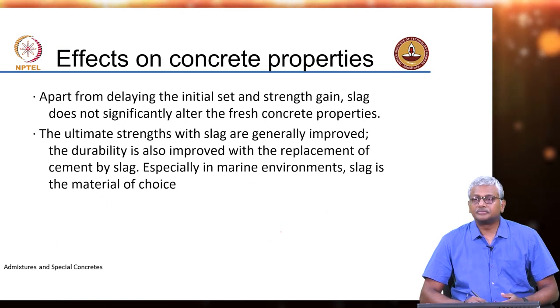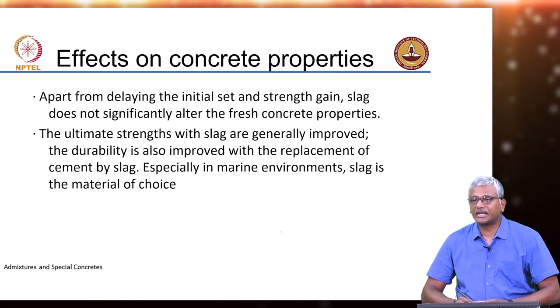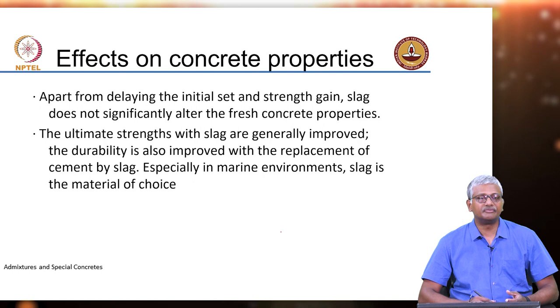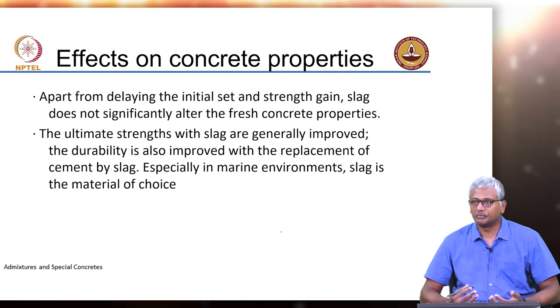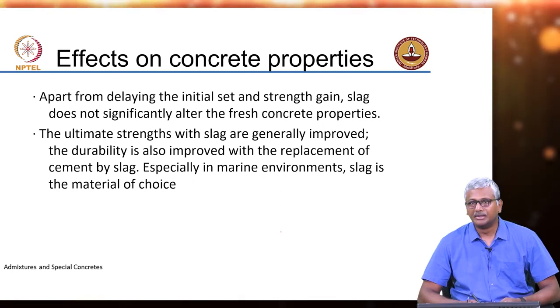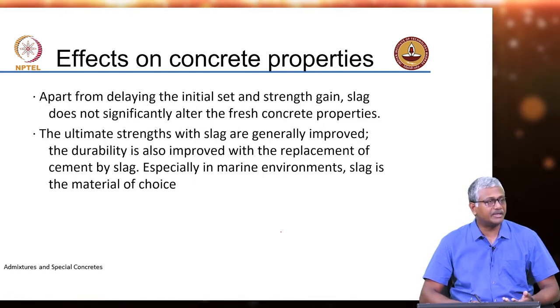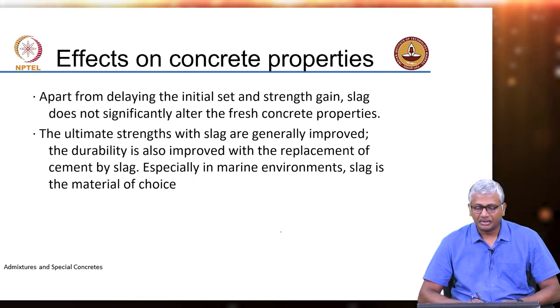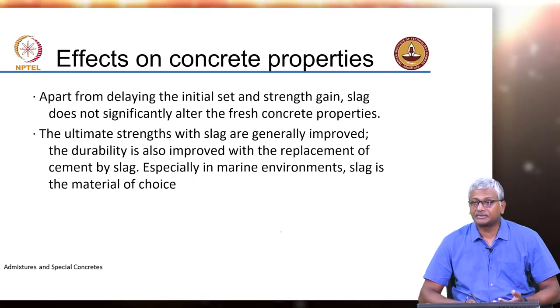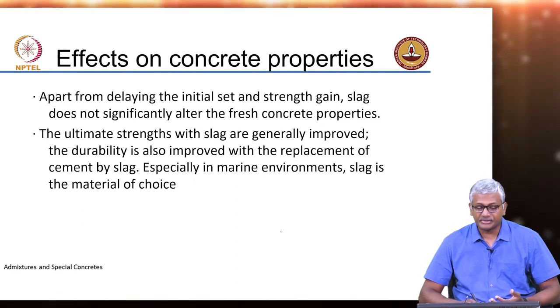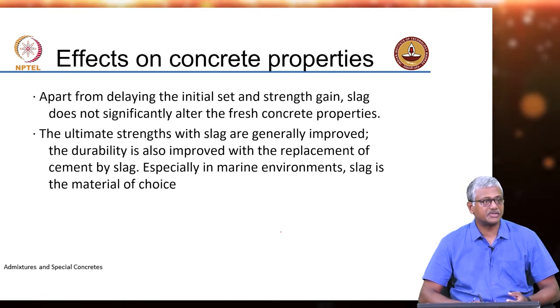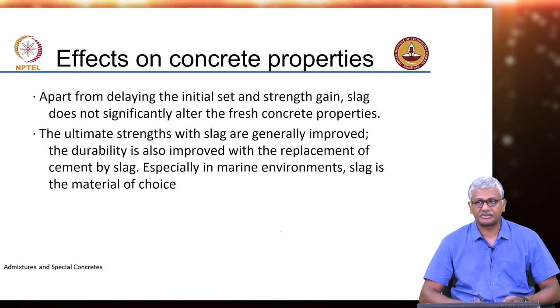Because of this, you will generally find slag concretes as having many unhydrated particles of calcium magnesium silicate phases. Now in terms of how slag affects concrete properties, it is not very difficult to visualize that because the slag reaction is slower, there will be a delayed rate of strength development. Apart from that, you will not see too much effect on fresh concrete properties when cement is replaced by slag.